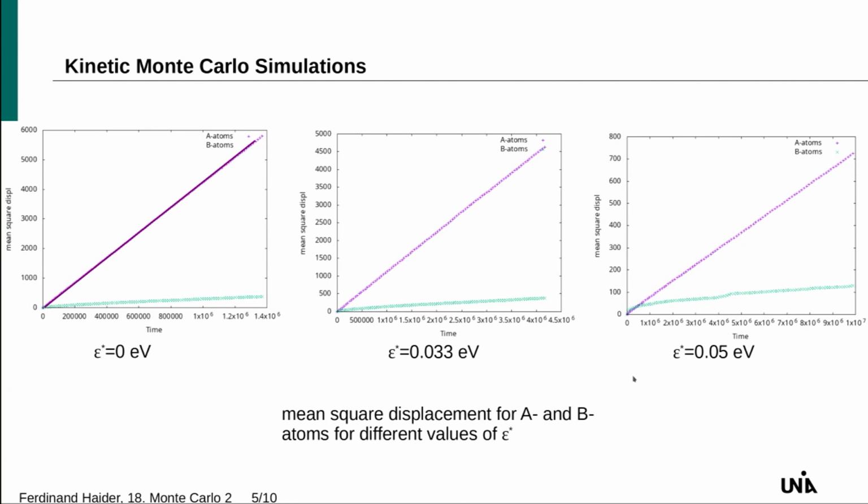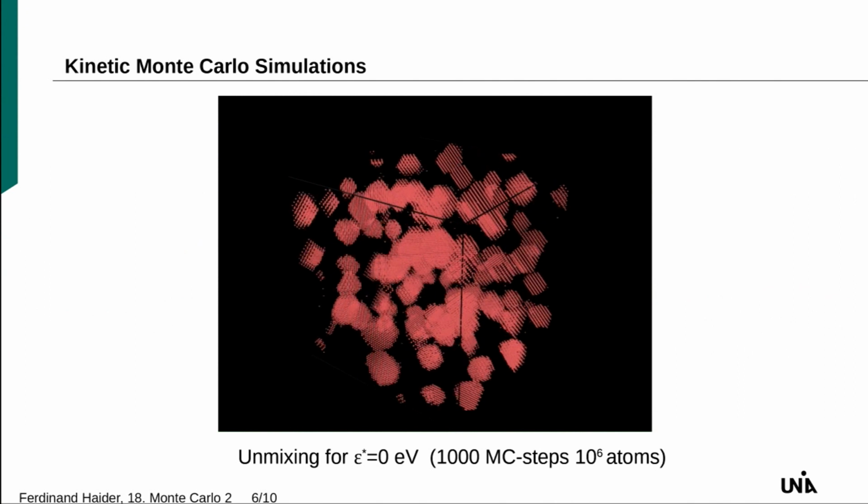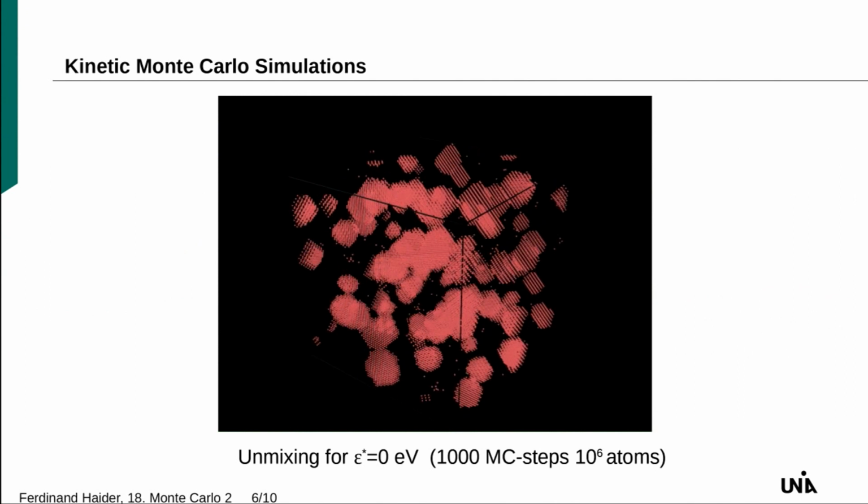Nickel aluminum is also such a standard case. So that's how one can try to get more realistic values for this case here, by taking experimental values for this ratio of diffusion coefficients, which are equal to the ratio of jump rates, and these you get from these mean square displacements. I don't know whether I have numbers here. No, I have just some